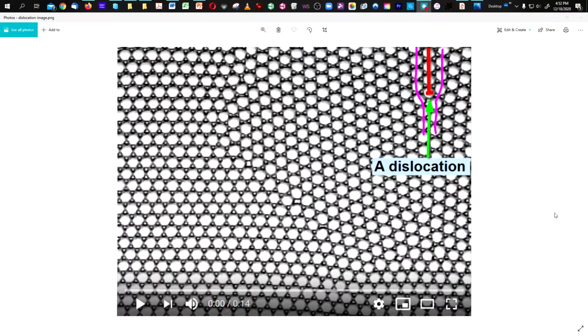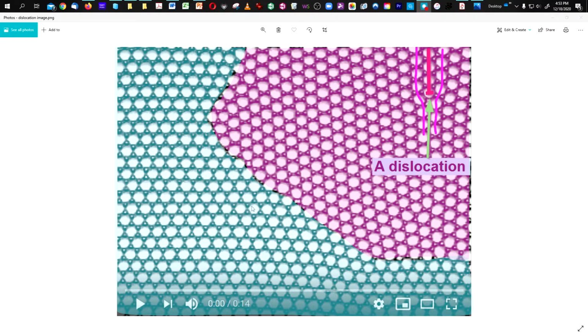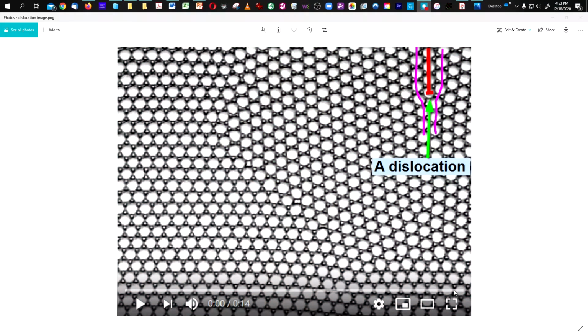But what we're going to look for, and I've highlighted up here in the upper right, is, first of all, before I talk about that, do you see the crystal grain boundary? I'm kind of tracing it out with my cursor right now. And you can sort of see that the alignment of atoms is different. Over here on the right is 1 crystal grain, and then down here on the bottom and to the left is another separate crystal grain. But in the crystal grain over here on the right, there is a little dislocation. Do you see the extra row of about 4 little atoms inserted between the 2 other rows that are highlighted in pink?